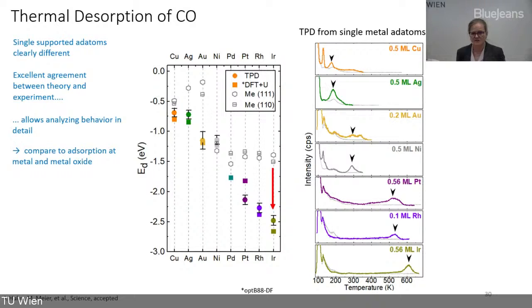This one is iridium. For iridium, the desorption temperature, the adsorption energy, is much, much higher. In fact, the single iridium atoms behave really like an iridium oxide substrate. Iridium is obscenely expensive and absolutely rare, but at the same time the absolutely best electrocatalyst. So this suggests that maybe supported iridium metal atoms could be really good electrocatalysts.